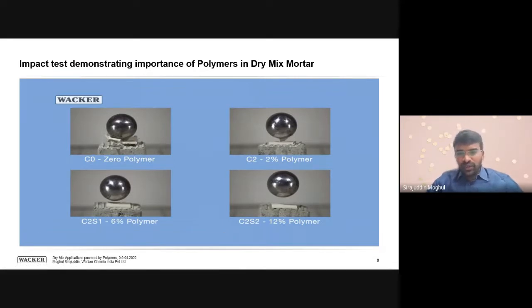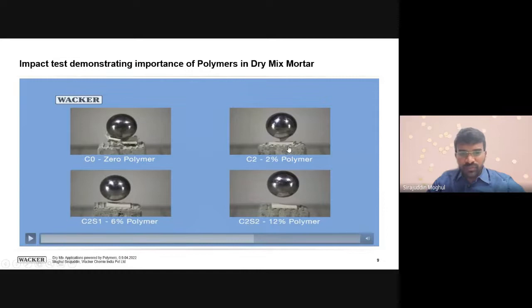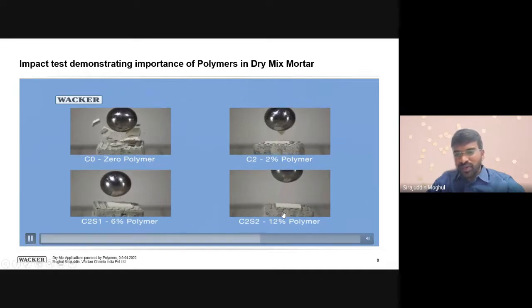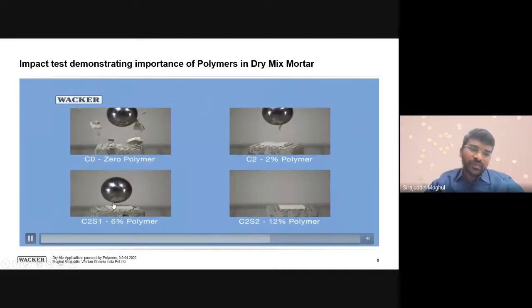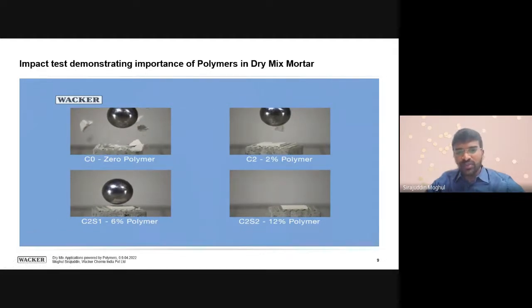Now, why I have paused the video here is, one thing we have to understand is, when the percentage of polymer in the mortar is zero, the tile has shattered, like what we see in our homes. And as we increase the percentage to 2%, a part of the tile has broken. When it is 6%, it is well intact. Now it is 12%. See, here the ball which has fallen on the tile is not rebounding. It has just fallen on it, and it is absorbing the complete shock. Here it is so strong that even the weight is able to take a rebound on it. See, the same ball, it is bouncing back, and it doesn't bounce back here. So that helps us understand how important it is to use polymers in some of the applications.